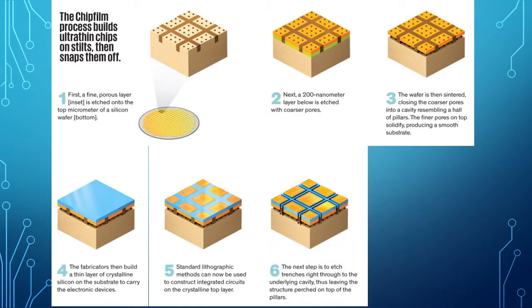The next step is to etch trenches right through to the underlying cavity, leaving only anchors at the corners or regions, which results in a structure perched on top of the pillars. This is done to keep the chips in a weak attachment to the substrate.